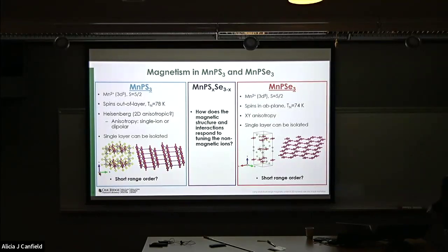There's some debate on the type of anisotropy and the type of Hamiltonian that should describe these materials, and I'll talk about that a little bit later. XY anisotropy has been proposed for MnPSe3. You need single ion anisotropy in this material. Maybe you have dipolar interactions as well. And in both of these materials, the single layer can be isolated, and you can see what happens to the transition temperature and the properties there.